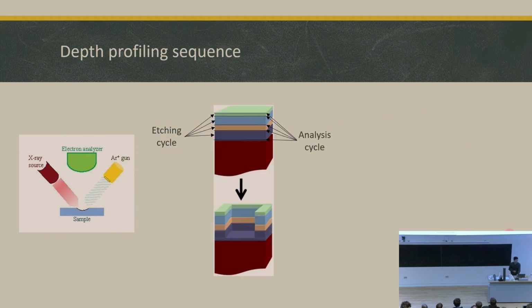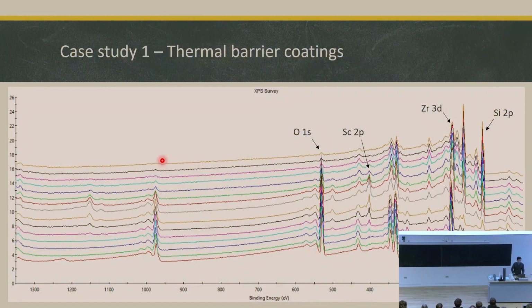I'll quickly go through how the technique works. Basically, we etch the surface with the argon gun, then use the X-ray source to collect the data, then etch again, collect again, so we can see from the surface layer to the bulk. Researchers here in the materials department try to make some thermal barrier coatings using elements including yttrium, zirconium, and scandium. The bottom spectrum we collected is the surface. Then we etch 14 times. We see the trend of scandium increasing, for example, then decreasing again, and other peaks start appearing.